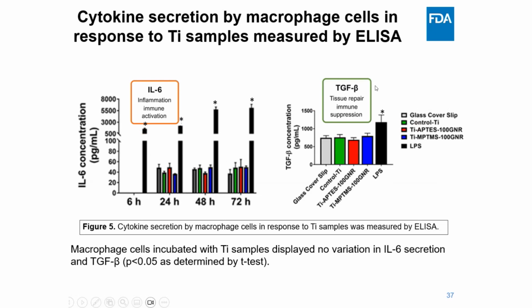We also look into cytokine secretion by macrophage cells next, as a way to assess inflammatory response to these gold nanorod-coated titanium surfaces. This was measured by ELISA, focusing on IL-6, a marker of inflammation, and TGF-beta, which is associated with tissue repair and immune regulation. The results show no significant changes in cytokine levels in response to these coated surfaces, suggesting that the gold nanorod coatings did not trigger an inflammatory response.